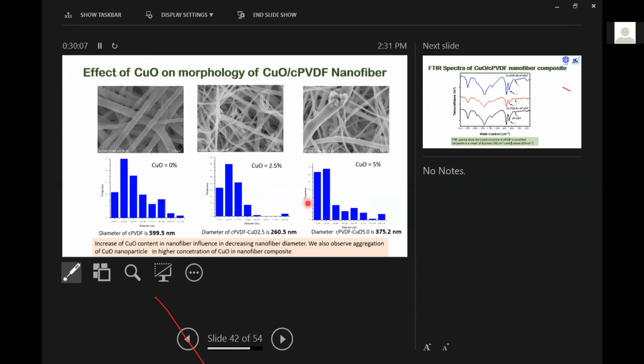So this is how we can make copper oxide cPVDF nanofiber composite. You can see here, without copper oxide, we can make a smooth nanofiber. But by adding the copper oxide, you can see the agglomeration of nanoparticle on the surface of the nanofiber.